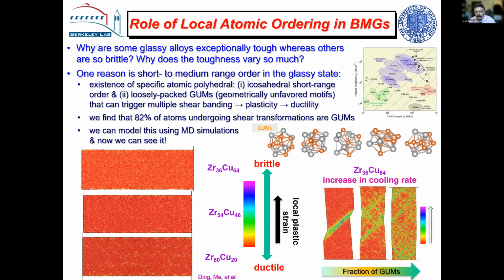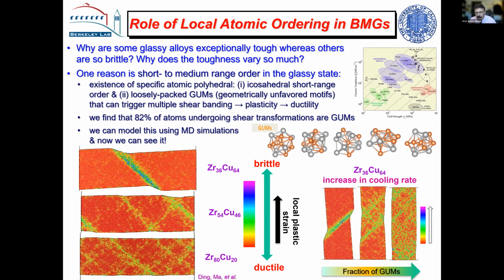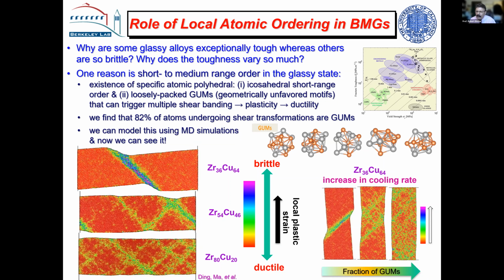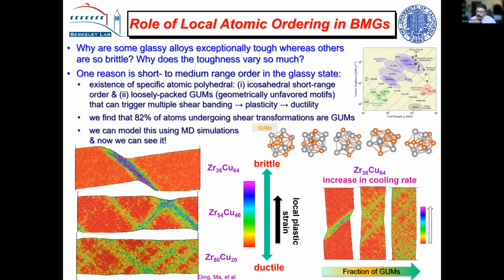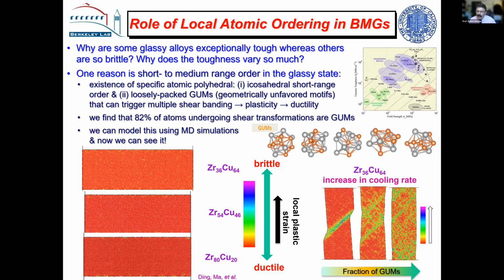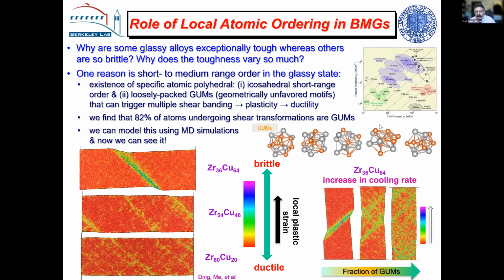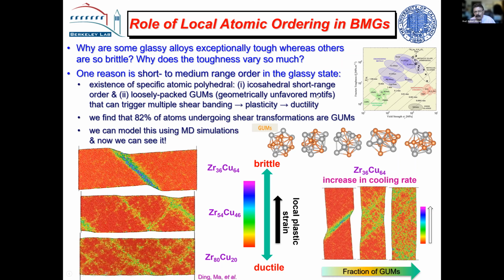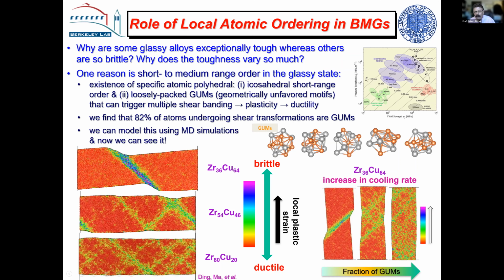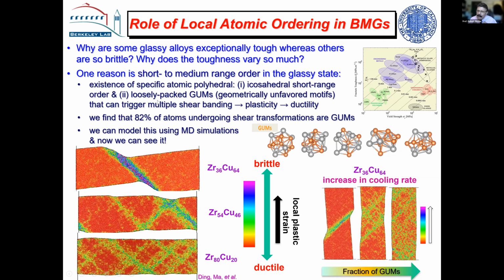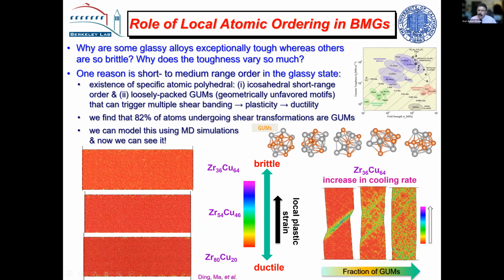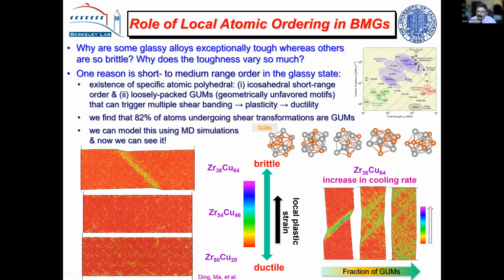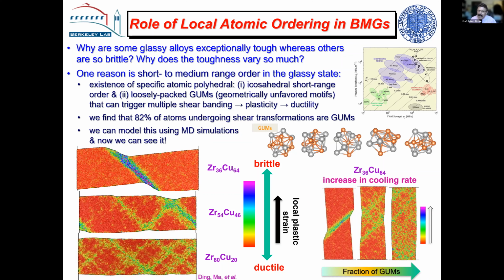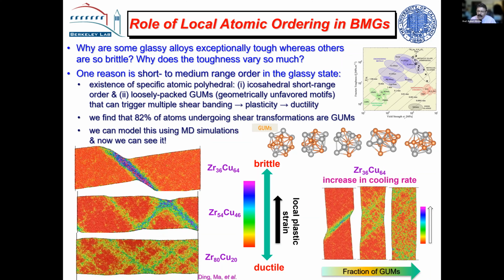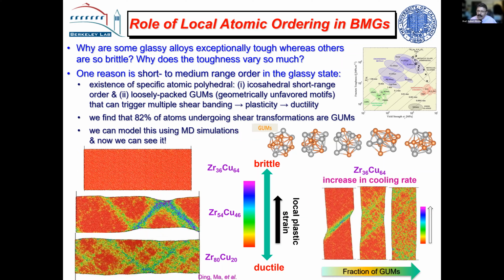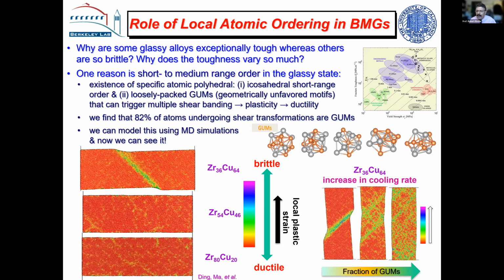It's kind of difficult to measure them. But some of these little motifs of atoms are not quite as stable. They don't have as much five-fold symmetry, and he gave them the name geometrically unfavored motifs, or GUMs. And they're more loosely packed, and because they're unstable, they can trigger shear bands. So the irony of this is if you can get lots of GUMs in the structure, you can trigger lots of shear bands, and that leads to plasticity in these materials.